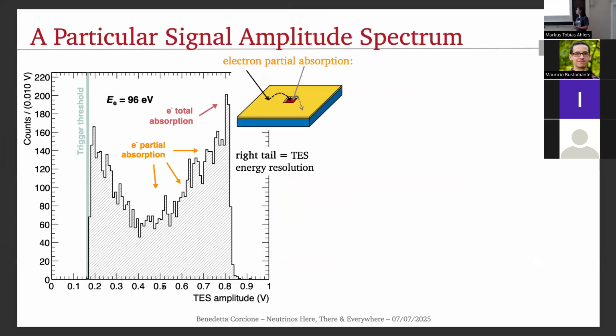So for each voltage tested, which means for each energy of electrons, we acquired the signals, and then we studied the histogram of the amplitudes of those signals. Here I reported the one for 96 eV electrons. What catches the attention here is that we are sending monochromatic electrons on the device, because we have a fixed voltage, so fixed electron energy. And these monochromatic electrons produce very different amplitude signals. This means that they release a different amount of energy inside the device.